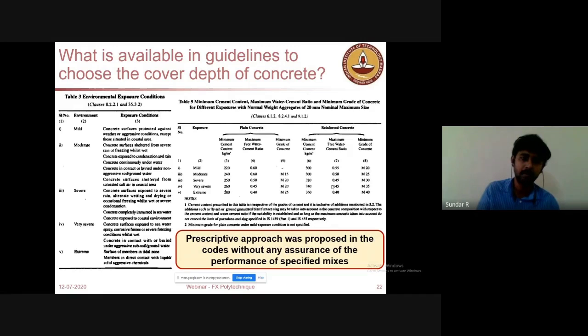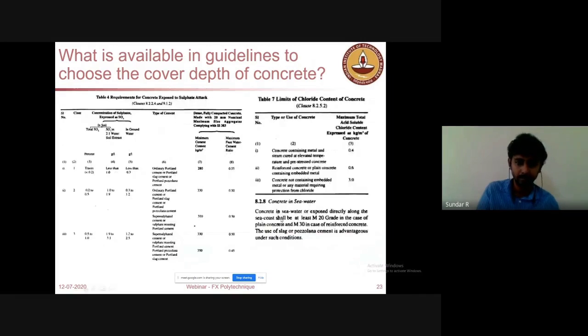Similarly, there are requirements for sulfate attack also, but still it is again the minimum cement content and maximum water cement ratio. So there is nothing we could know about new concrete. Similarly, for concretes in seawater, there is a specification regarding the minimum strength grade which can be used, but there is no information to assess the concrete after casting, whether it has sufficient resistance against the ingress of harmful compounds or elements for the steel embedded in concrete as well as the cement matrix.